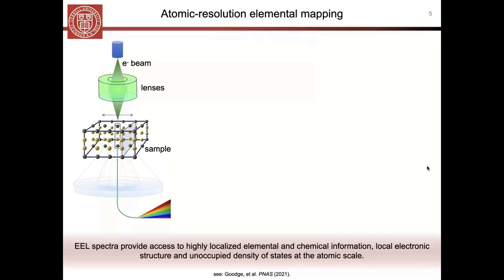As most people know, we take the STEM probe and shoot it through a crystal, and we collect the forward scattered electrons and disperse them in terms of energy. That gives us something that looks like this, which we usually look at on its side. And this, of course, is an EELS spectrum. You'll see emerging from the sloping inelastic background these characteristic peaks, which, again, most people know can be related back to specific orbitals and specific bonding in specific elements.